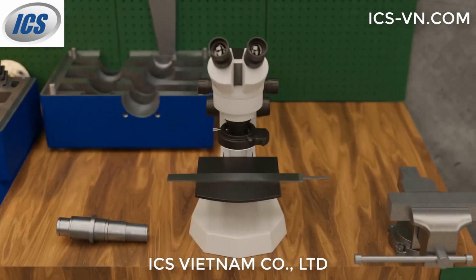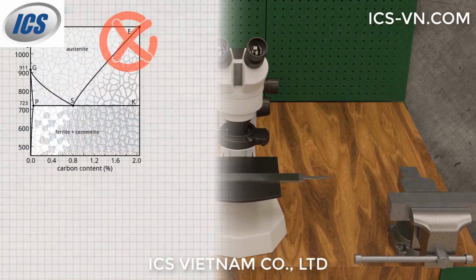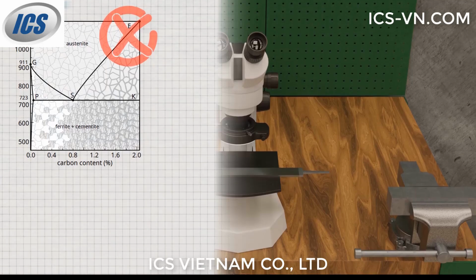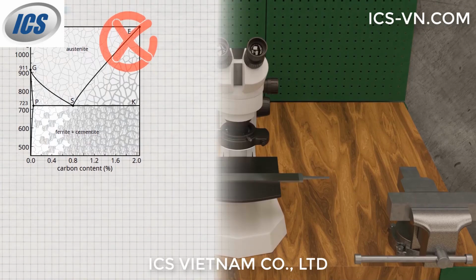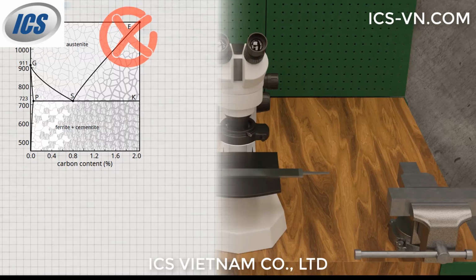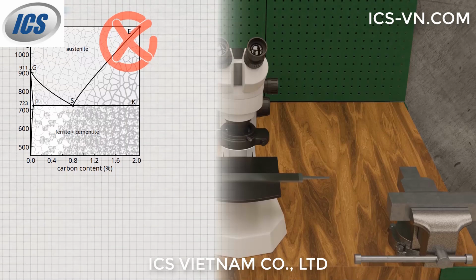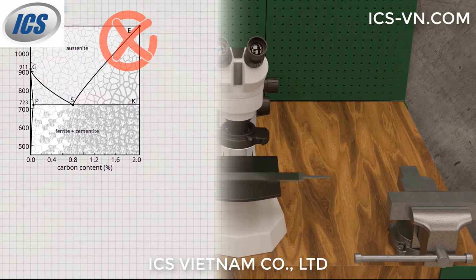Note that the formation of martensite can no longer be explained by the iron-carbon phase diagram, since such diagrams are basically only valid for relatively slow cooling rates, at which a thermodynamic equilibrium can always be established in the microstructure. However, thermodynamic equilibrium is deliberately prevented during quenching, so the iron-carbon phase diagram is no longer valid in this state.